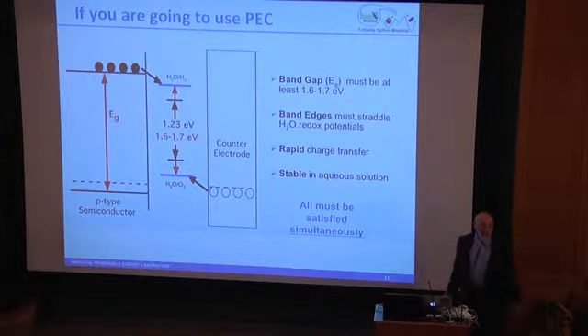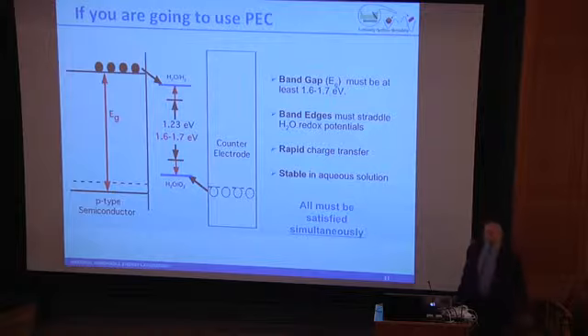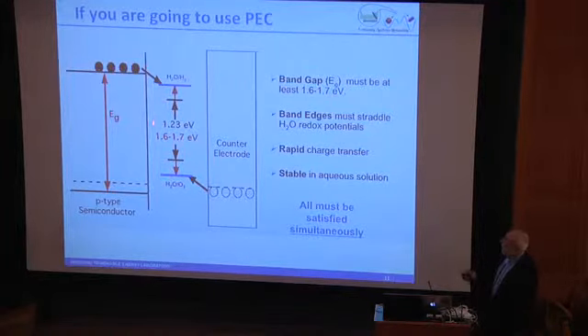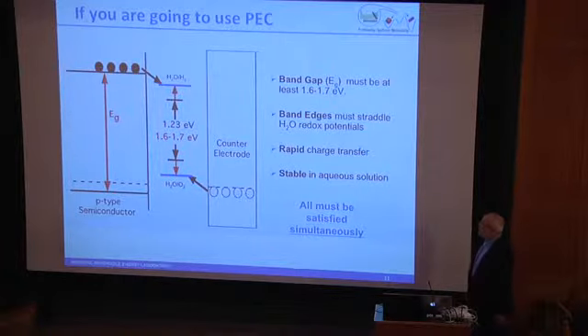ideally, and most practicable systems have been in the order of 2 volts, which is starting to get to the point where you're a little bit over where you'd like to be in terms of the band gap of the material. So this is what it looks like, and obviously where your semiconductor band edges are is important. Where this couple sits versus them is important, and how to get there from a first principles calculation is not entirely trivial.